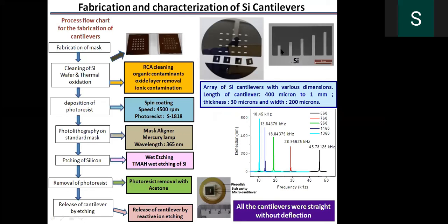We also measured the mechanical integrity of the transducers, like these cantilevers, by measuring the resonance frequency, and the resonance frequency is found to be inversely proportional to the length of the cantilevers. So this essentially shows there are no harmonics in this one. It is only a single frequency that I am going to use. And this is the processing technique.